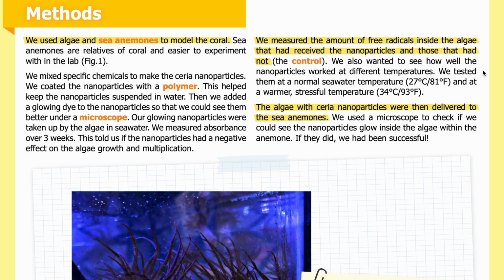We tested them at a normal seawater temperature, 27 degrees Celsius or 81 degrees Fahrenheit, and at a warmer, stressful temperature, 34 degrees Celsius or 93 degrees Fahrenheit. The algae with ceria nanoparticles were then delivered to the sea anemones. We used a microscope to check if we could see the nanoparticles glow inside the algae within the anemone. If they did, we had been successful.